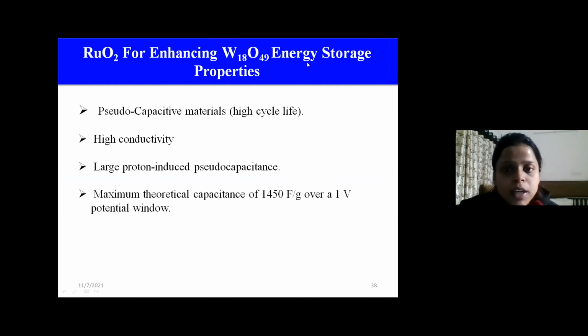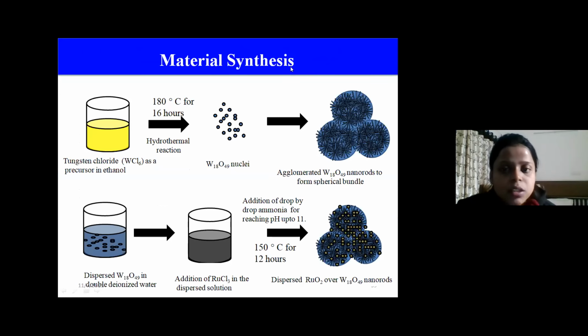So RuO2 for enhancing the energy storage properties of W18O49 is a pseudocapacitive material with high conductivity, and its theoretical capacitance is also 1450 farad per gram, which can be a good solution for hybridizing it with W18O49. So we first used a solvothermal process for the synthesis of W18O49. Then we used a hydrothermal process by dissolving this W18O49 in water, and then we added the ruthenium oxide precursor in the solvent and used the hydrothermal process for the synthesis.